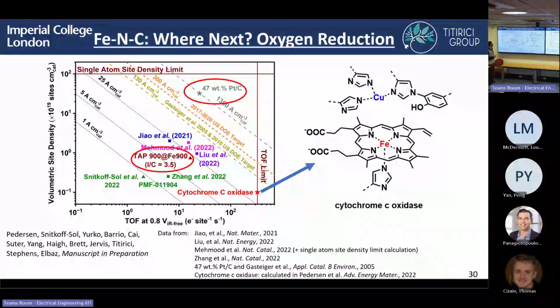So then the question is, where do we go from here? This is essentially, on the y-axis, the volumetric site density, so how many sites you have per volume, versus the turnover frequency at 0.8 volts. This metric is important when you want to consider transport applications, because you're really limited by space. So you want to consider the number of sites that you have per volume.